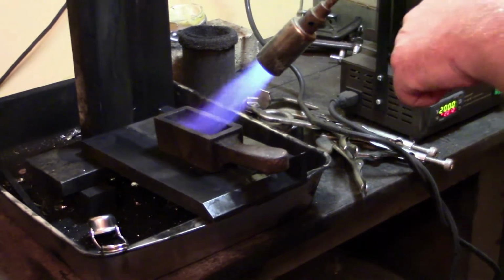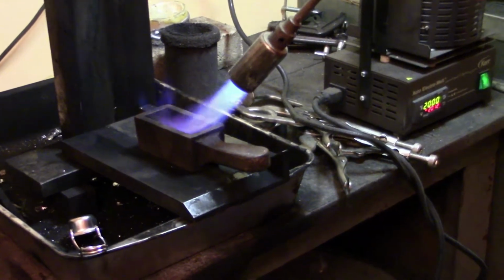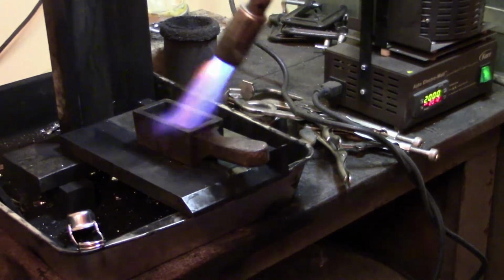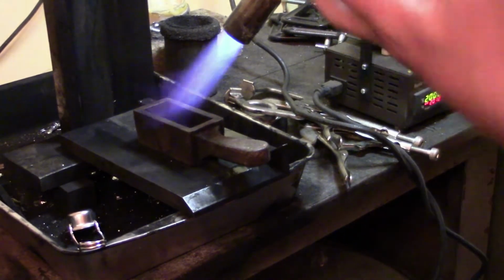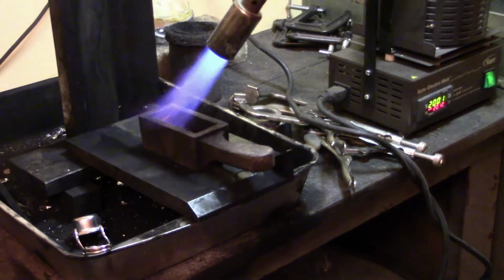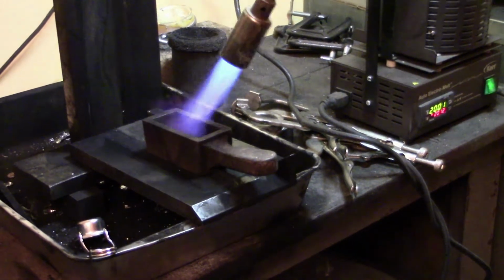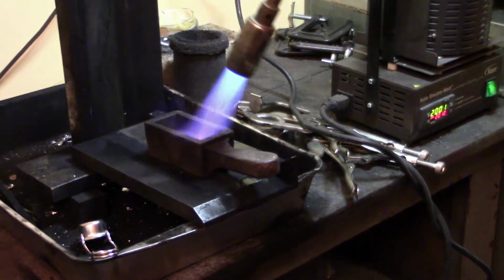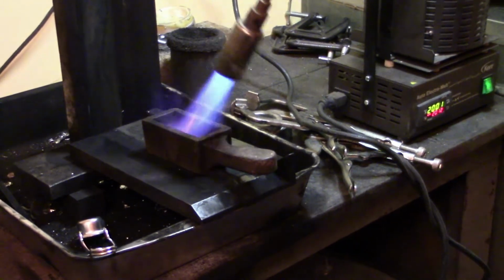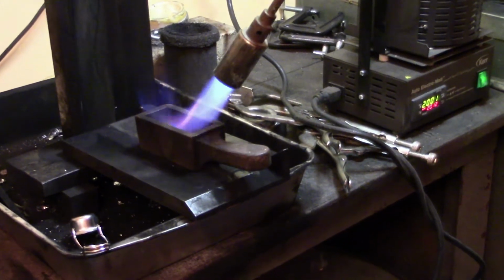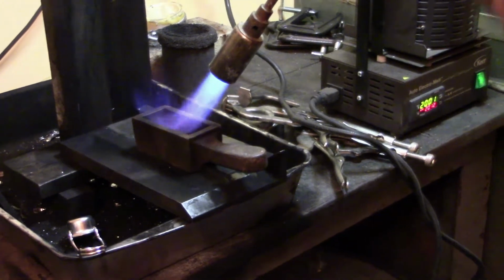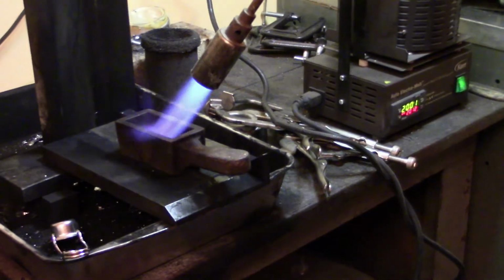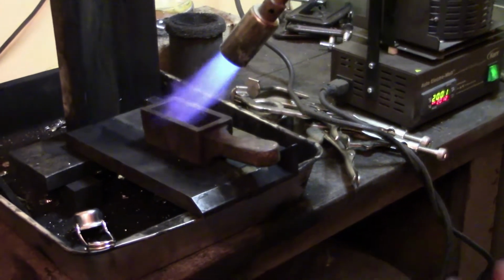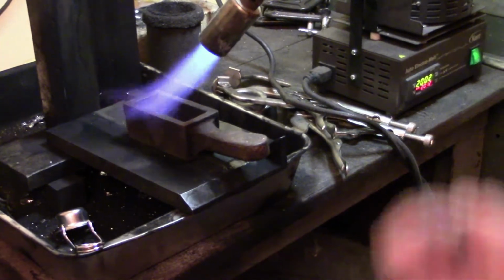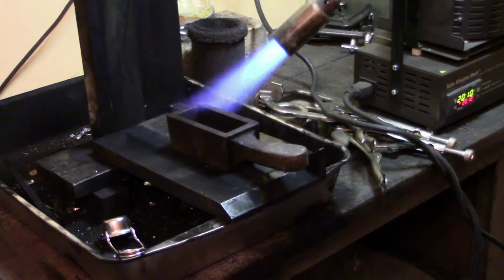What I'm doing now is I'm actually sweating the cast iron, and what I mean by that is when I put heat on it like that, the condensation around it is going to come off and it'll appear wet for a second as it condensates, and then that's going to evaporate as it heats up, because there's a danger in casting liquid metal into cold metal, because that condensation can form quickly and actually explode.